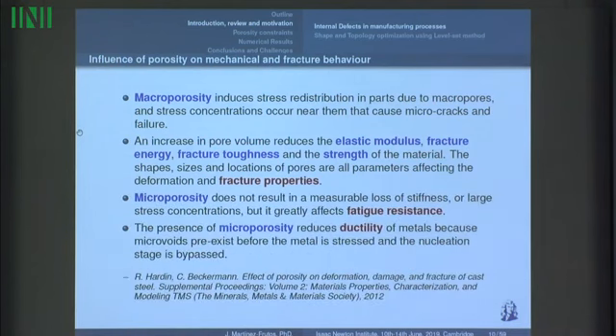Here we have some relation between this porosity defect and the mechanical and fracture performance of the final casting. So there are some references. One of them is this one by Hardin that studied the effect of porosity on the deformation, damage and fracture of cast steel, and basically it depends on the size of the holes. So macroscopic porosity introduces a redistribution of the stress inside the solid, and also there is a stress concentration around the macropores. So this can cause micro cracks and failure.